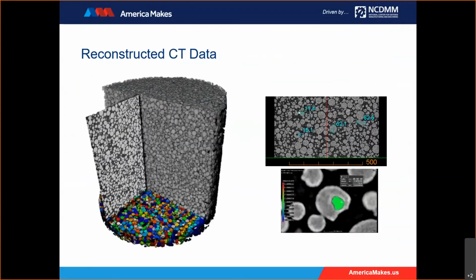On the left, we can see what a 3D reconstruction volume looks like. And on the right, you can see a 2D slice through the volume where we can start to see some high density bright particles in the top image and porosity colored in green in the bottom image.